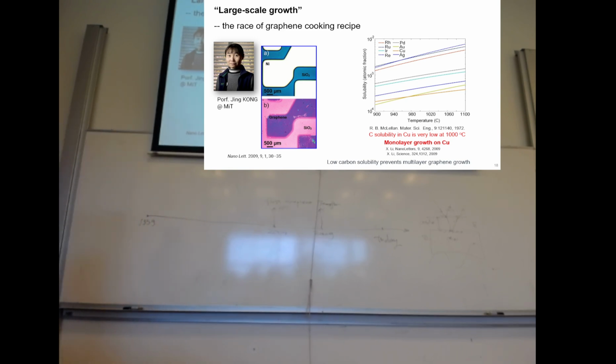And then a lot of good cooks, like experimentalists, have found that actually there are a lot of metallic materials which can form graphene layers on top of them. But there is a very important parameter, which is the solubility of carbon atoms in the bulk. The lower the better. Why? Because you don't want to precipitate very thick graphene layers. Like this one is already thick, because nickel somewhere is not plotted there, but there were some other materials. For example, copper has very low carbon solubility at around 1,000 degrees C. 1,000 degrees C, that's a hot temperature.